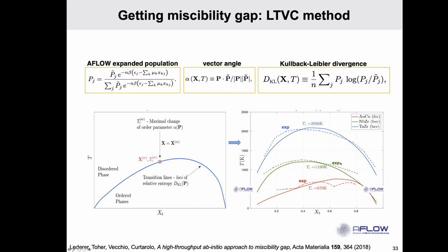Look at the niobium and look also at copper gold. For copper gold, you might complain, oh, well, listen, what are the other three things here? The reality is that our model says that there is only one miscibility gap, okay? In reality, in copper gold, there are three. There is one like this, and one like this. So what we get is the envelope of the miscibility gap. If we wanted to know what's going on, we should have done one line here, one line here, one line there, and then we would have got three. But a priori, you don't know, okay?